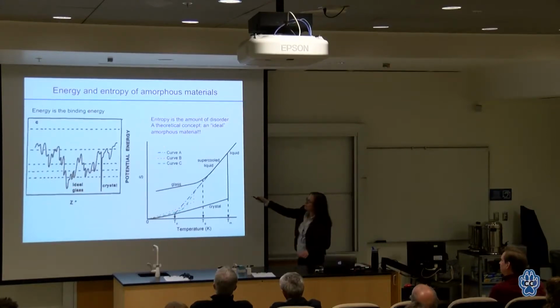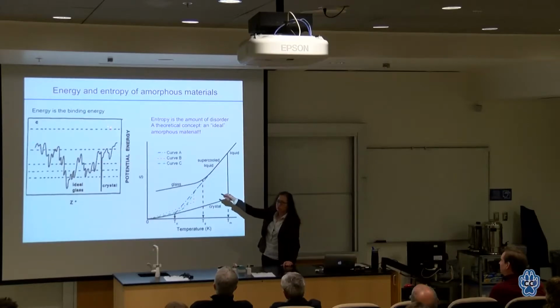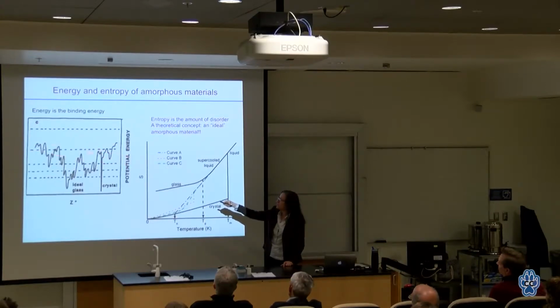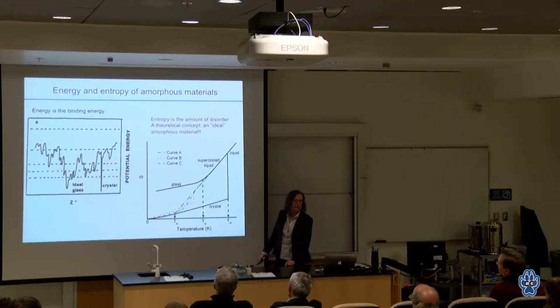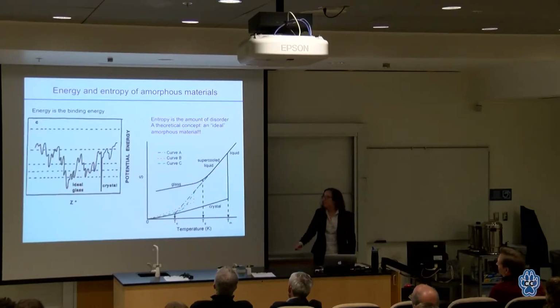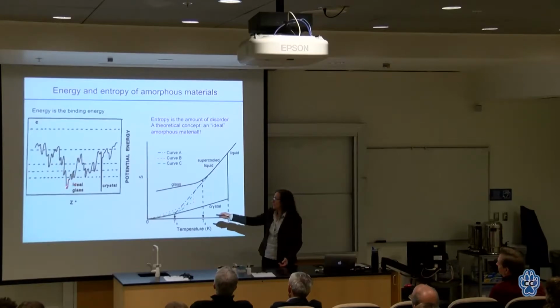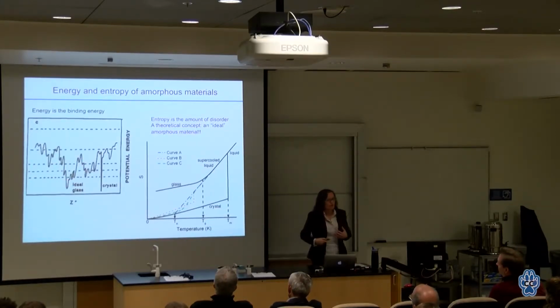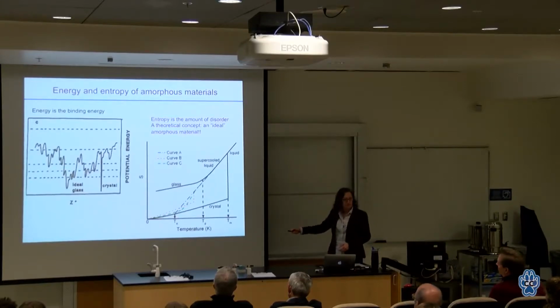So the problem is, and the reason there's all these lines here, is usually what happens is you're cooling down, you start at high temperature, and you're bouncing around between all of these states. And as you cool down, you get trapped into one of these basins. And so you never find that state. Even if you found it in one part of the sample by accident, another part of the sample would be over here. So you don't find that state. But it is out there theoretically. This is not completely made up.